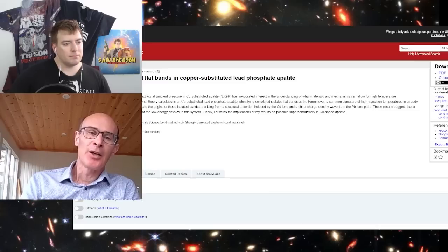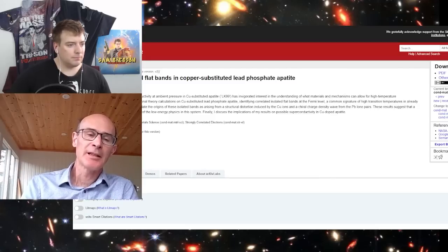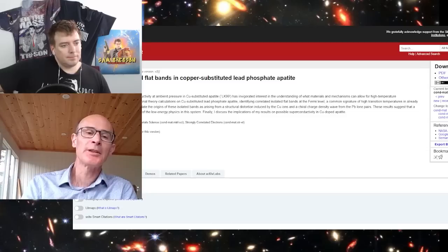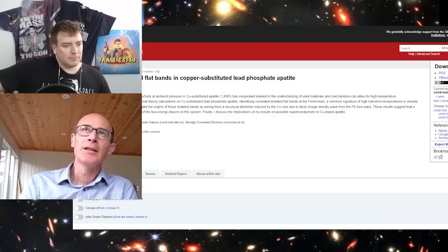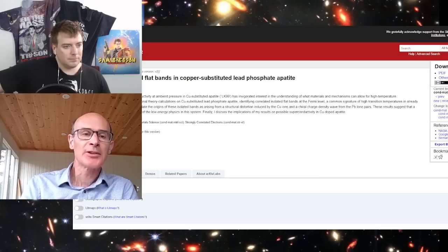The band structures that you get are what you would expect for a rather dilute set of copper ions in a salt. You would have these very narrow bands, almost isolated levels at the Fermi level, which just corresponds to copper being in the +2 oxidation state.